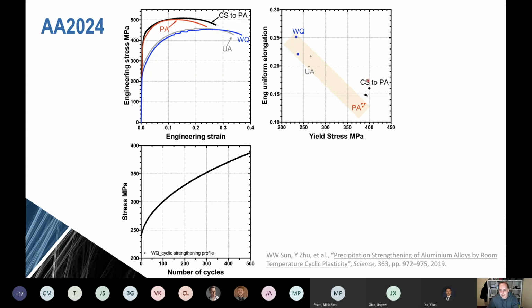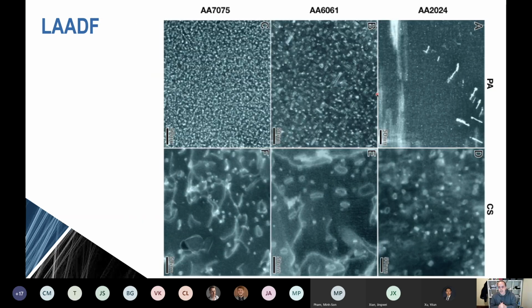Now, if we look at these sorts of microstructures, what's really happening in the microstructure? You can see here some TEM micrographs. These are low angle annular dark field images. And what we've got is for the 7075, the 6061 and the 2024, we've got 2 images each.